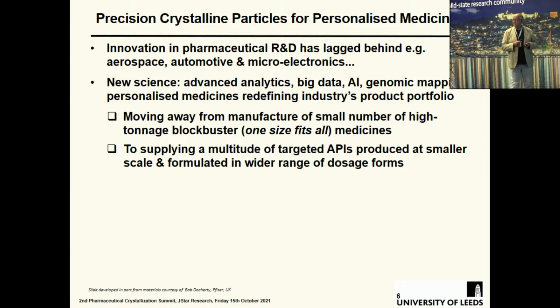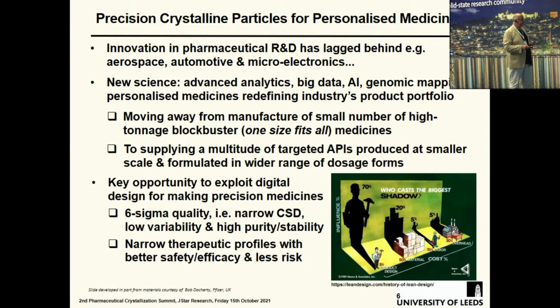If you take breast cancer, you can't have a single treatment for that. It's a biological predisposition issue, and there are at least 20 different variants of it. One medication doesn't do it. So where we're going is supplying a multitude of targeted APIs produced at a much smaller scale and formulated over a wider range of dosage forms. Typically, drugs are formulated in 3 dosage forms: small, medium, and large. The reason is that the burden to get through the regulatory authority is quite high, and we want to reduce that. So we'd ideally like a dozen dosage forms and a dozen medicines for every one. This is the key opportunity to exploit digital design for making precision medicines.